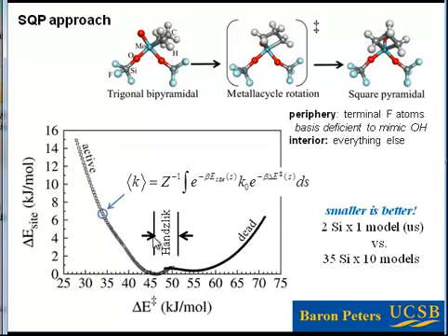Now notice the 10 sites that Handzlik made, which were all carved from crystal structures, they all have similar low energies of formation, and they're all very near the same range of activation energies, right? So it appears that doing this in this rather ad hoc way, choosing a crystal and cutting things out of it, really doesn't capture the wings of this distribution well. In fact, you could argue that it's missing a big chunk of the distribution.